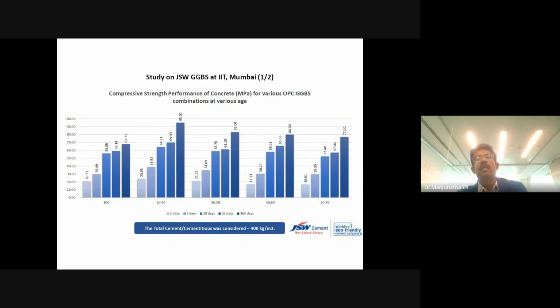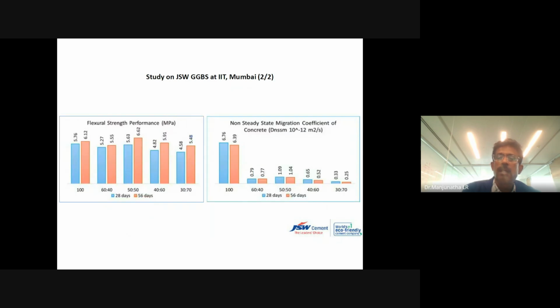We have done various studies. At IIT Bombay, we have done a study for almost 1 year on M40 grade concrete, and we have measured the strength gain over 3 days, 7 days, 28 days, 56 days, 90 days, and 365 days. We have got excellent, phenomenal results. Flexural strength, chloride migration, chloride efficiency we have also done. You can see that the higher the replacement of OPC cement by slag, the lower the migration coefficient. 50% replacement is always said to be ideal. Only for mass concrete you can go up to 60%.